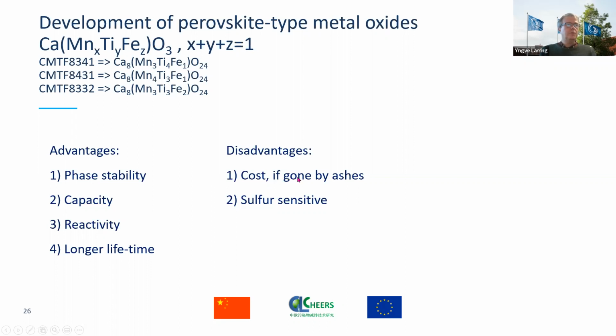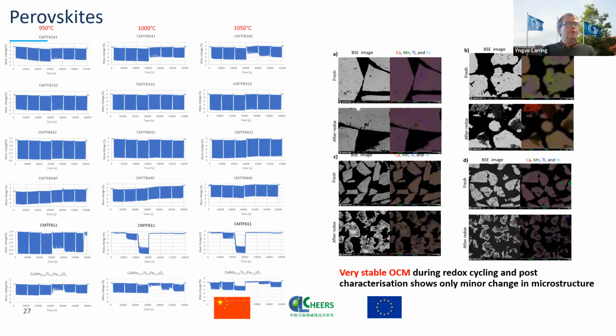The disadvantage is, of course, cost, especially if it's taken away by ashes, but petcoke has low ash content. It also has some sulfur sensitivity, which can be a disadvantage, but not necessarily detrimental, depending on the process. The perovskite shown here at the top is the most stable one, with the most titanium. It has slightly lower capacity than the next two, which have lower titanium content. But in this one we didn't see any degradation in the microstructure, while this one shows some degradation of the microstructure down here. Still, that is very decent after such a harsh test as this TGA.